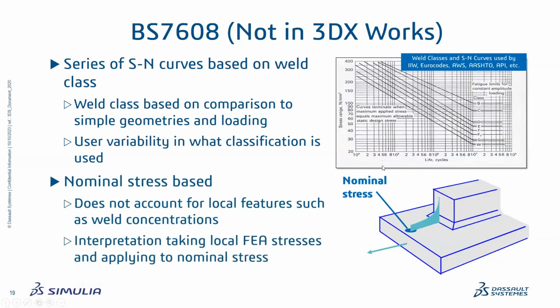One of the reasons is this is often a nominal stress case. Think about a 4-point bending where you've got a constant stress region. You nominally know that, you put a small attachment on and you weld it, and you're really looking at your calculation of this stress life curve from that nominal stress. But in FEA, we always get the local stress. So determining what is the same nominal stress on your generic structure can be difficult and lead to interpretation. And as well, you also have to choose which curve is most appropriate.